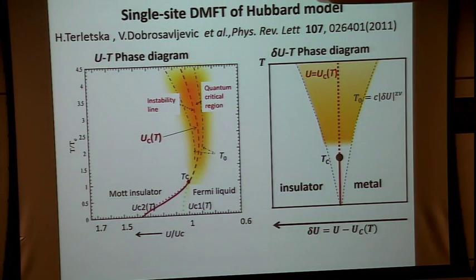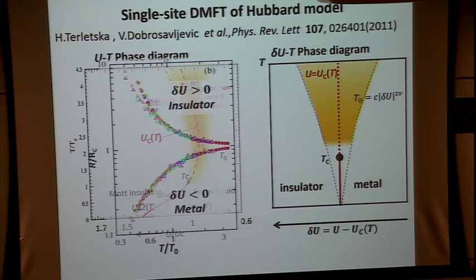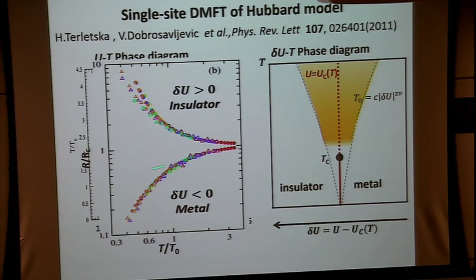Okay, but this is experimental data. Our experiments were motivated by the theoretical studies conducted by Brad, Dobrosavljevic, and Terletska. They calculated the conductivity using the DMFT framework, and this is a well-known phase diagram deduced from the DMFT, with the first order transition line and critical point here. In these regions, they calculated the resistivity, and the resistivity follows the quantum critical scaling. That was a theoretical suggestion. And later, we examined the behavior in real materials, and we obtained the results which I explained.